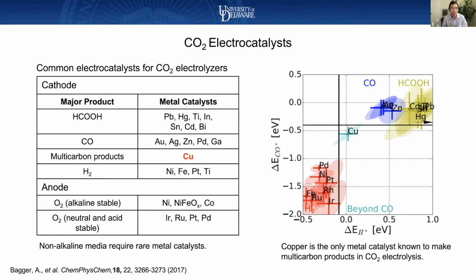Hydrogen is something you don't want to produce in CO2 electrolyzers, and there are certain metals that are extremely active for hydrogen evolution, and therefore they are really bad catalysts for CO2 reduction. On the anode side, oxidation is the reaction we are considering, and based on the environment, if this is a highly alkaline environment, then you can use non-precious metals like nickel, nickel iron oxide, or cobalt-based catalysts.